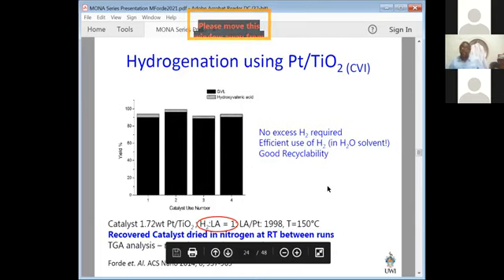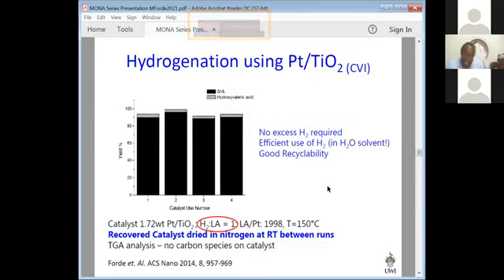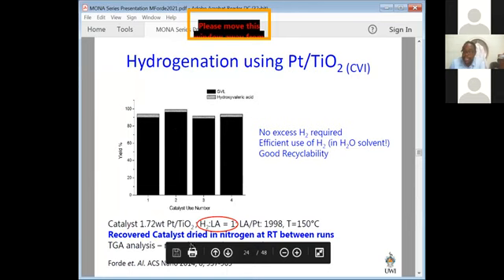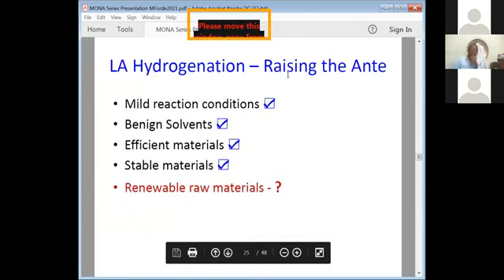It turns out that the material is actually stable without rehydrogenation, and that was quite a surprise. However, we've not got any further information in terms of in situ characterization. So that means operando experiments, where we run the experiment and at the same time perform the materials characterization. And hopefully one day we'll be able to get onto that. So it's a good system and it works well. The question is, from that hydrogenation, my question always was, could I do better?